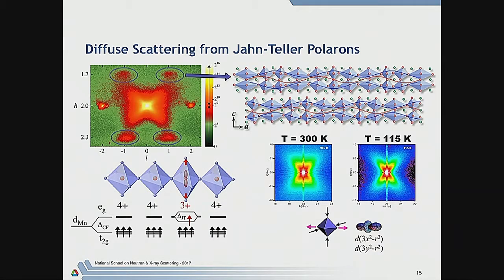And what that tells you, if you ever see an incommensurate peak like that, is that there's some modulation in the system. It's slightly incommensurate, which means that the modulation does not peak at discrete positions, but actually has what looks like a charge density wave modulation. And so here you see this Jahn-Teller modulation is long, then short, and it's long again, short. So it's actually a longitudinal Jahn-Teller modulation, which diffuse scattering by analyzing the intensities of all of these peaks.